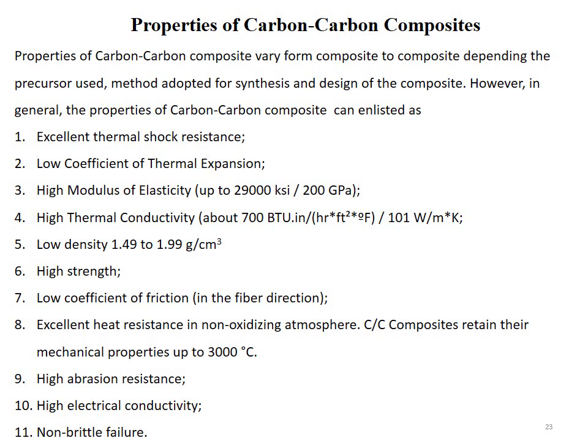They have also very high strength. Carbon-carbon composites have low coefficient of friction in the fiber direction, excellent heat resistance in non-oxidizing atmosphere. Carbon-carbon composites retain their mechanical properties up to 3000 degrees centigrade provided that there is no oxygen in the atmosphere. High abrasion resistance, high electrical conductivity, and non-brittle failure are also the general properties of the carbon-carbon composites.